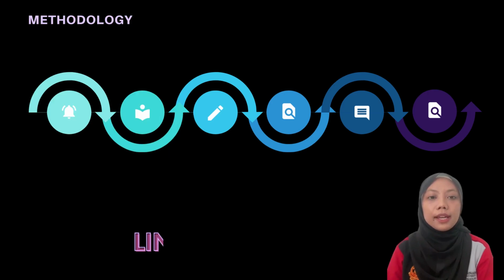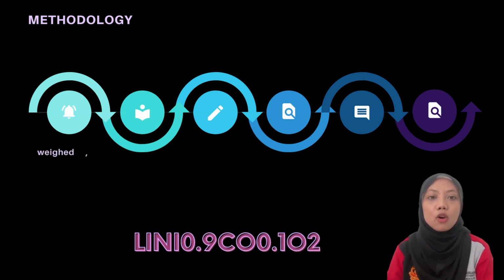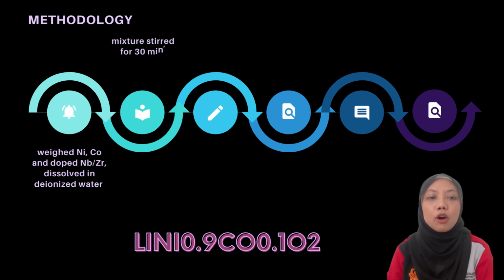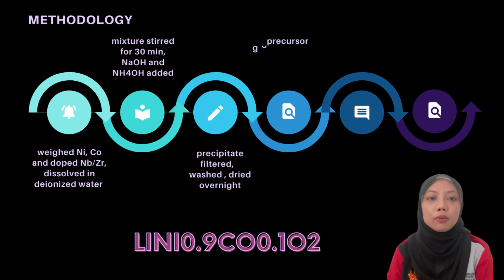To make LiNi0.9Co0.1O2, the mass of nickel, cobalt, and dopant was weighed and dissolved separately in deionized water at room temperature. After that, the mixture was stirred for around 30 minutes to obtain a homogeneous solution. Then, sodium hydroxide solution, and an appropriate amount of ammonia solution as a chelating agent, was added to the mixture. After that, the precipitate was filtered and washed several times, then dried overnight. The precursor obtained was ground using an agate mortar to get fine powder.